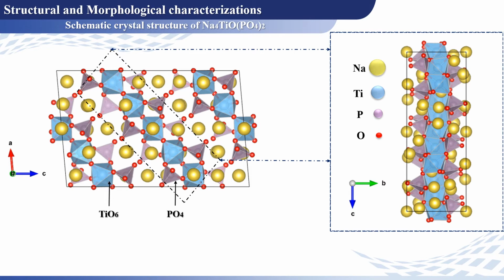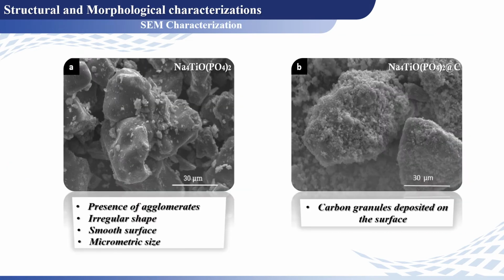between these chains. The morphologies of our uncoated and coated material were examined by scanning electron microscopy. As shown in the images of the uncoated material, the particles are agglomerated with an irregular shape and have a smooth surface, while from the images of the coated material we can see fine carbon granules deposited on the surface.